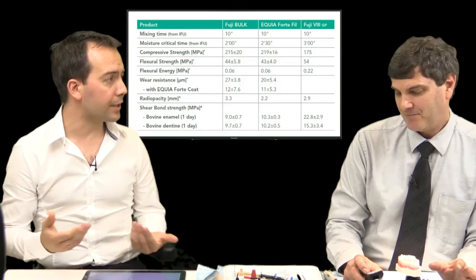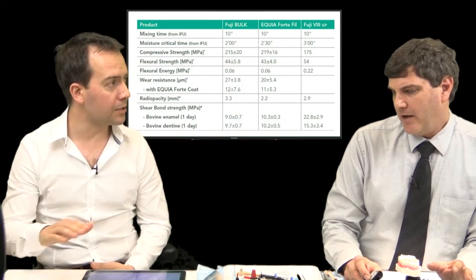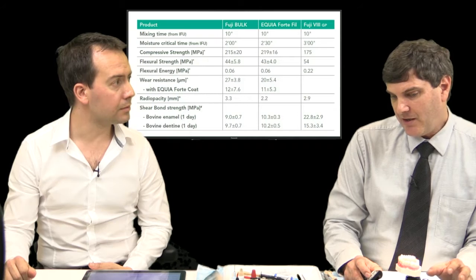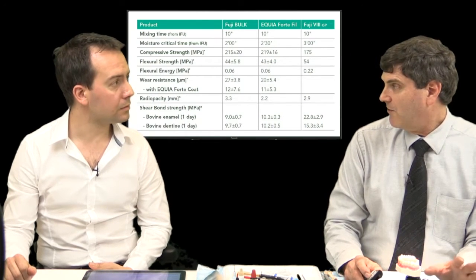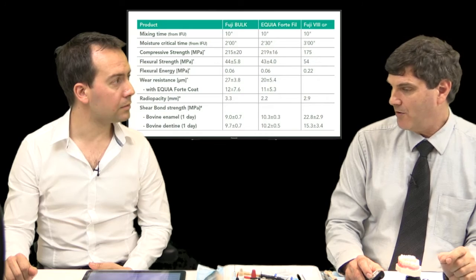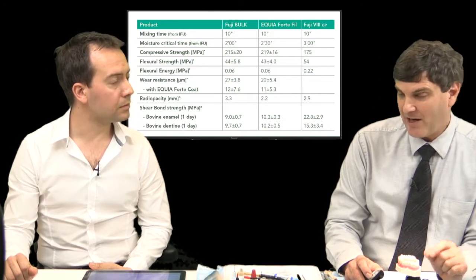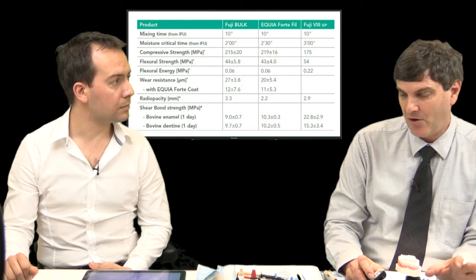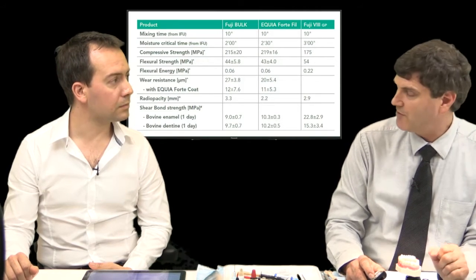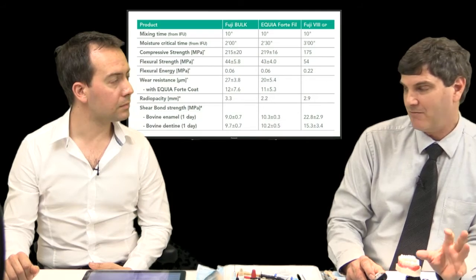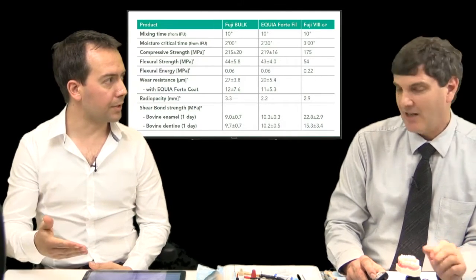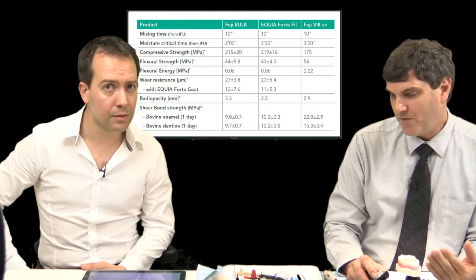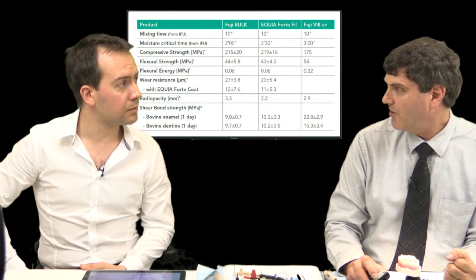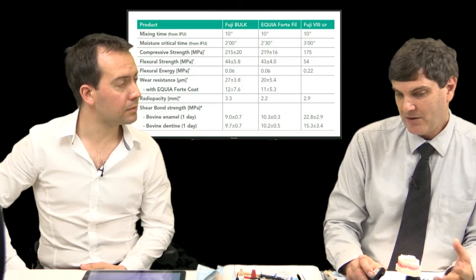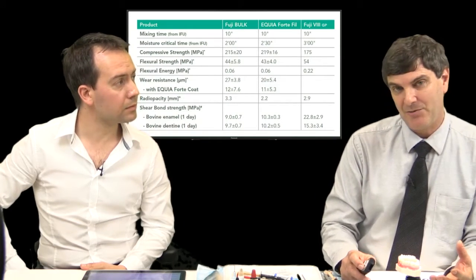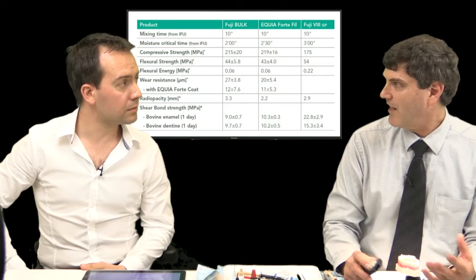Does that moisture include things like Fuji Bond LC if you're using it in a sandwich technique? No, absolutely not. If you're using a hydrophobic, resin-only based bonding system, it's fine. What we have to be careful of, though, is if you're going to put an all-in-one type bond over the top of this. Some of these are aqueous based solutions, so the all-in-one etching and priming systems or aqueous primers, you don't put those on your glass ionomers because they will actually create some moisture contamination until after that moisture critical time. Understood. So for those that want to move forwards quickly, they need to use purely the bonding component. So if you've got a 2 or 3 bottle system, use the last bottle, because that last bottle is the one that only contains the resin. It won't have any of the aqueous primers in it.